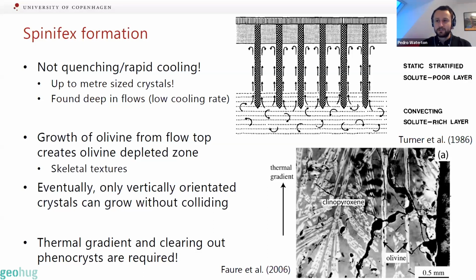So there's a lot of debate exactly about how spinifex form, but the one that Nick and I settled on, and that we think there's the best evidence for, is essentially the random spinifex at the top is coming from fairly rapid cooling. There's quenching, and you get a sort of chill margin. And then underneath, you start to grow these dendritic olivines. And then what happens is, because you're growing olivine from the flow top, you actually create this zone that is depleted in olivine components. And so you can only crystallize more olivine with a fair bit of undercooling. And this starts to give you skeletal textures.